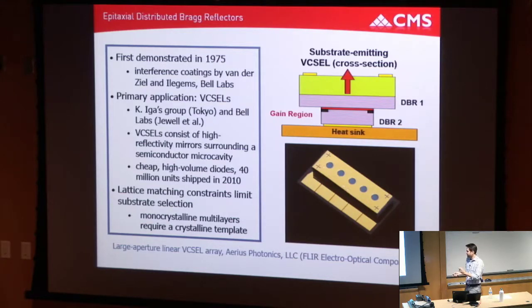So it's an interesting class of semiconductor lasers because it emits vertically through the surface of the device. You can make them in large 2D arrays, etc. So the technology for making interference coatings in the single crystal systems existed since the early days of the ion beam sputtered films. But again, it's basically limited from this lattice matching constraint to being grown on a lattice matched planar gallium arsenide base wafer.